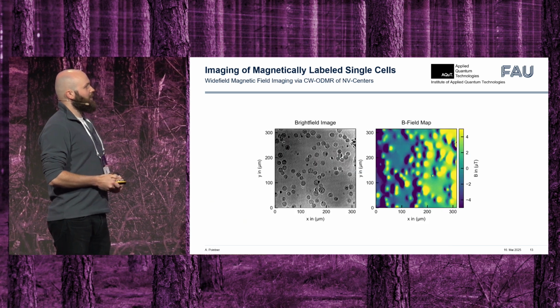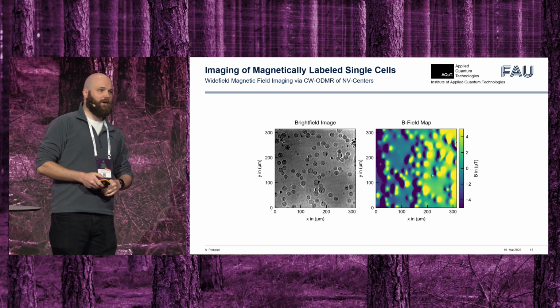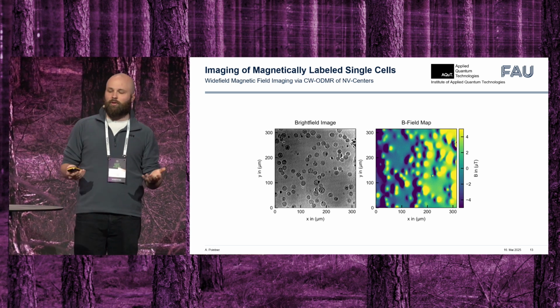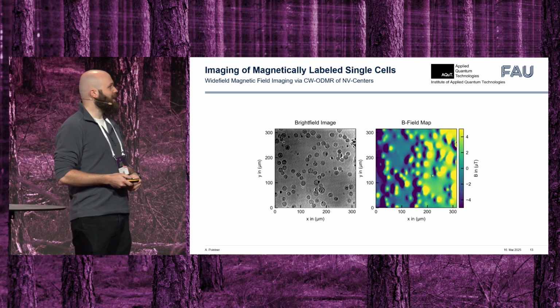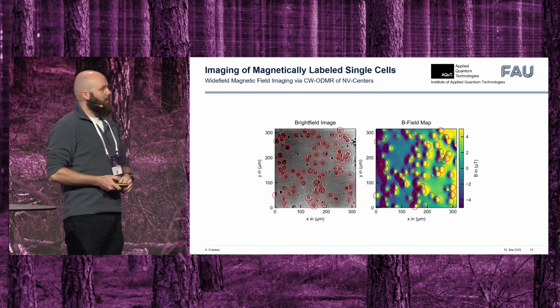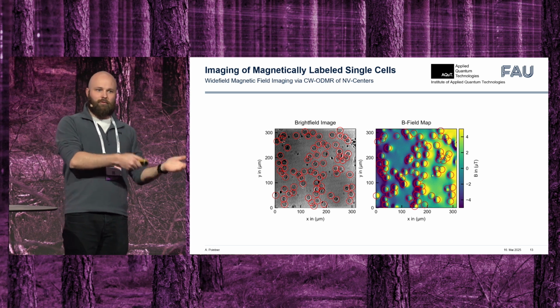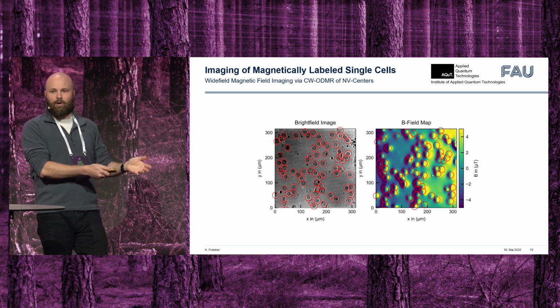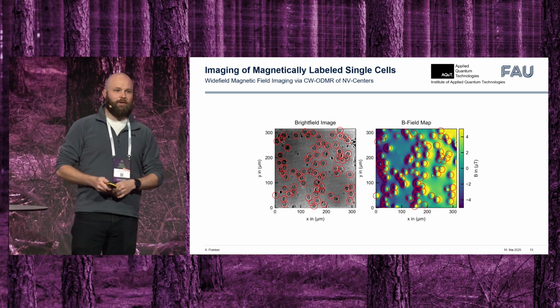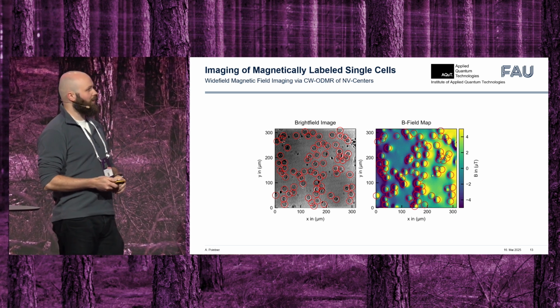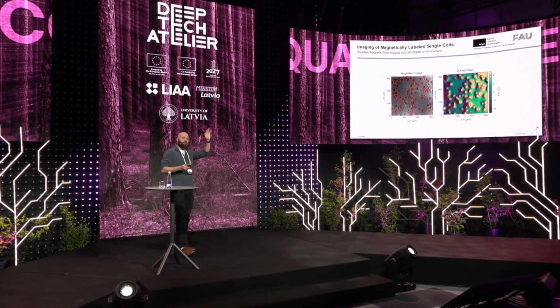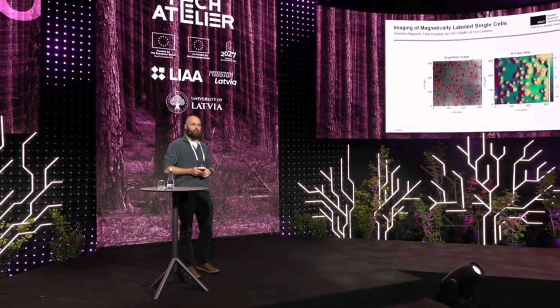And this basically gives us a magnetic field camera that can see magnetic fields with the microscopic resolution required to resolve individual cells. And we can see a direct bijective relationship between what we observe with classic bright field microscopy and what our magnetic field microscope can see. The interesting thing now is that we are completely irrespective of any tissue surrounding it. So even if we would put a few micrometers of tissue above our cells, we would still be able to see them with our magnetic field microscope, which is where the classical microscopy breaks down.